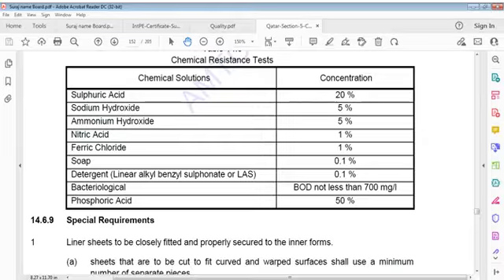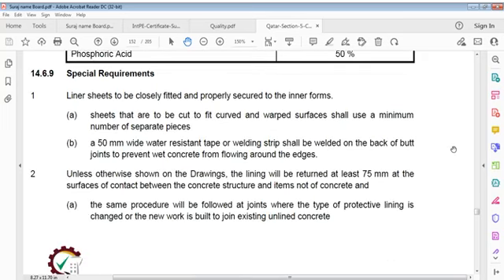Special requirement. Sheet to be closely fitted and properly secured to inner forms. Sheets that are to be cut to fit curved and warped surfaces shall use a minimum number of separate pieces. A 50 mm wide water resistant tape or welding strip shall be welded on back of butt joints to prevent wet concrete from flowing around edges.